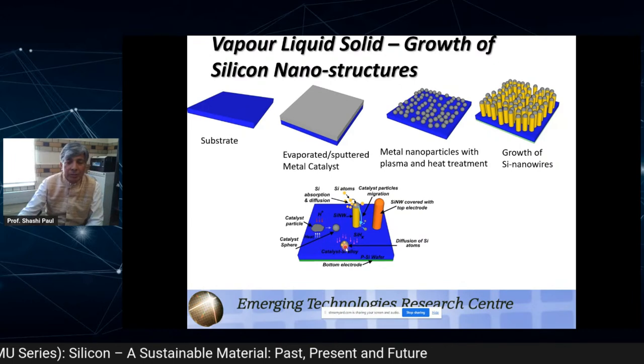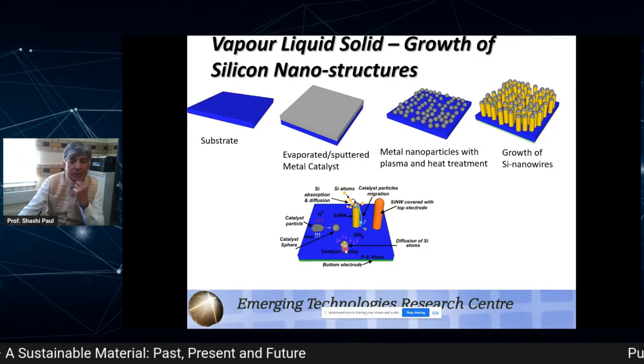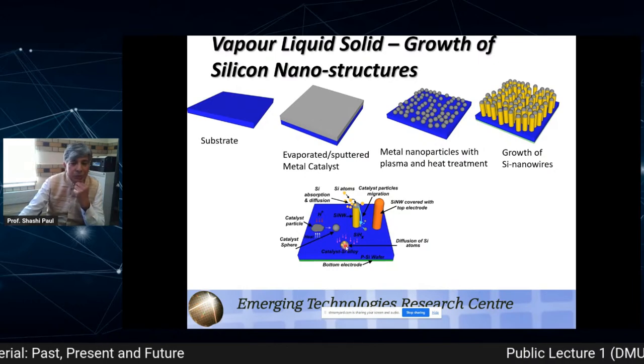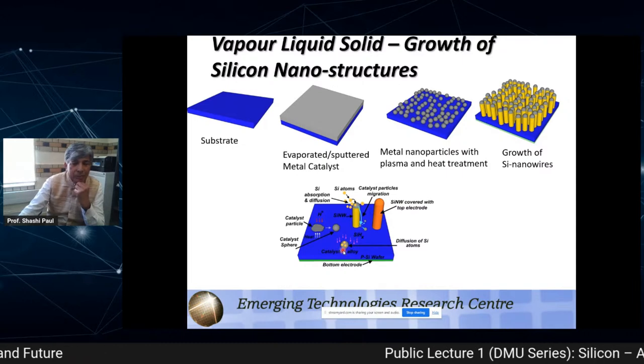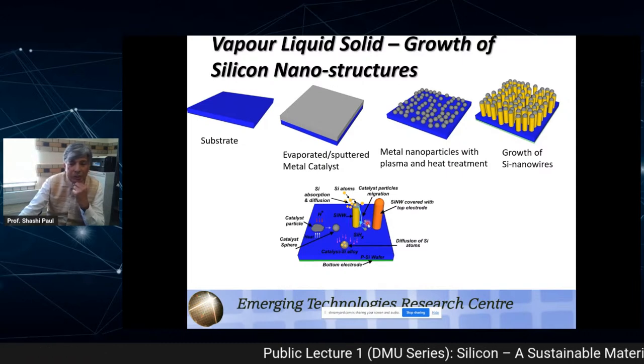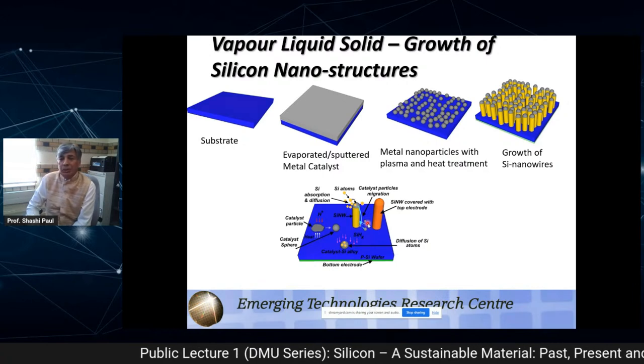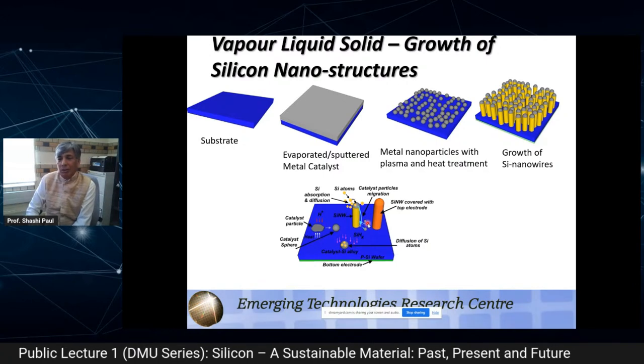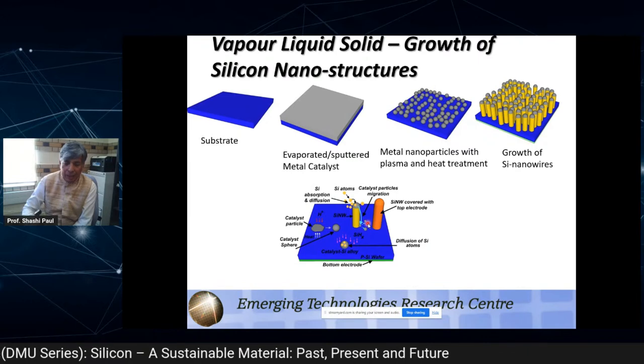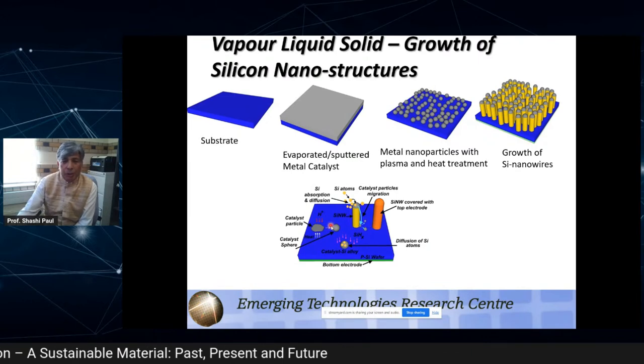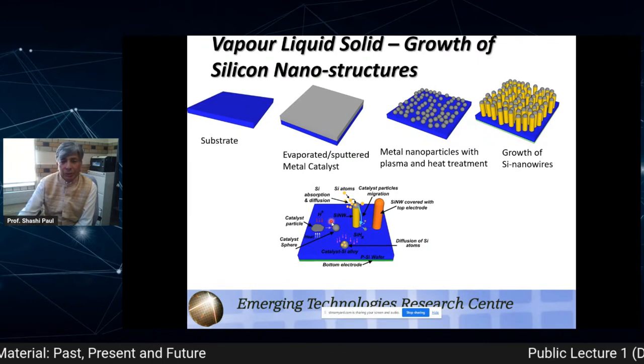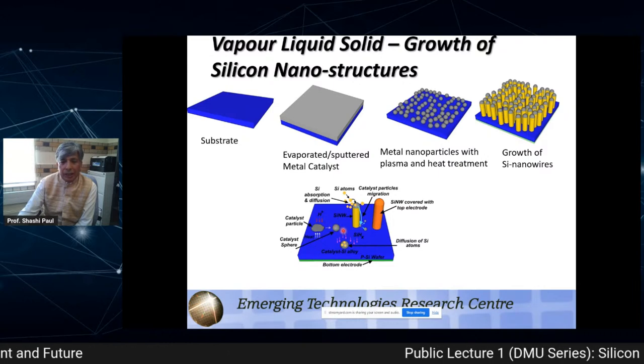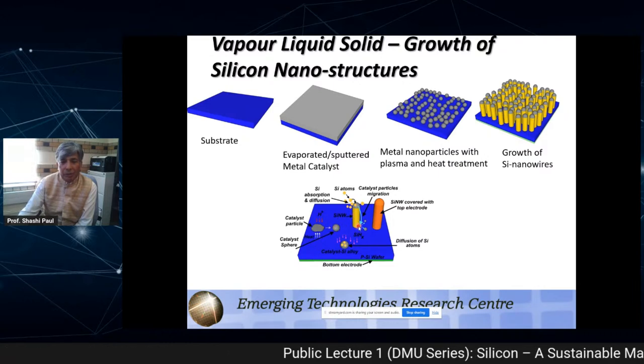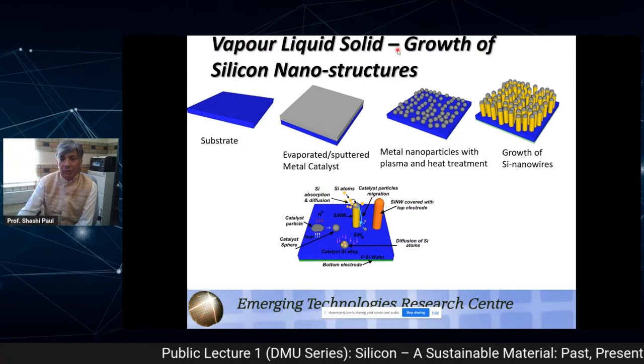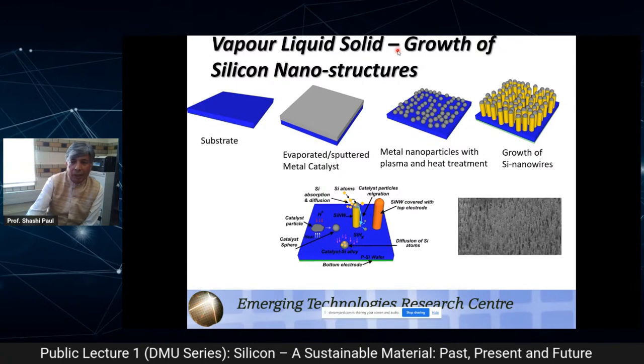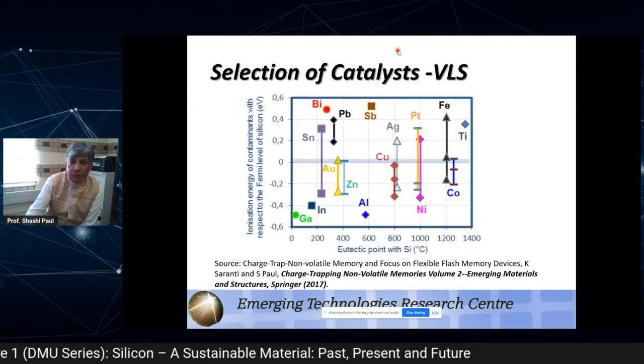So what happens? Silicon keeps dissolving in it, it reaches supersaturation, and then it spews out, generally from the bottom, and forms these solid structures. So you can make these silicon structures at around 400 degrees centigrade or less. You are bringing vapor of silicon into this liquid, which dissolves it, and finally forms a solid. That is why it's called vapor-liquid-solid growth. So you can make all these things.